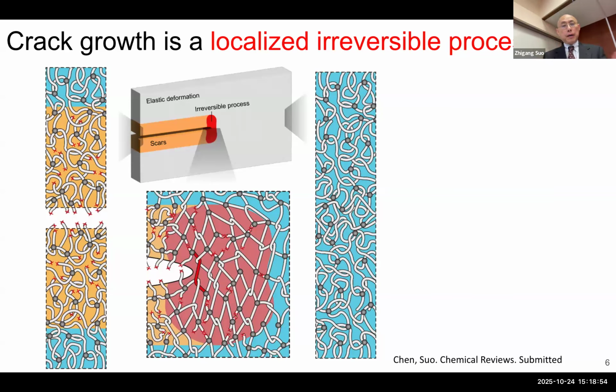Anyway, here's a crack growing in a polymer. We are going to focus on a very important class of crack growth, in that it's a localized irreversible process, in the sense that the majority of the material is still elastic. The reason being, in most applications, you want the material to be more or less elastic. You want to use it repeatedly: reload, come back, reload, come back. You don't want plastic deformation, it's complicated. So the materials are mostly elastic. However, if you have crack growth, of course at the crack tip you have an active irreversible process, in the sense that you are going to break chains. That's irreversible.